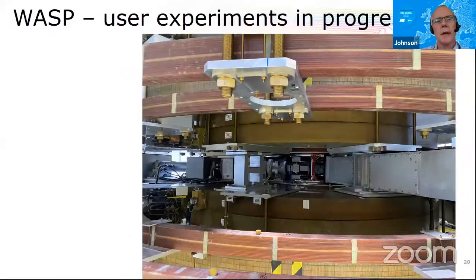So a new instrument, no X-ray capability in this case, wide-angle spin echo. So this instrument has taken some time to deliver. It was a very, very challenging project, but now it's in user service, doing user experiments. For those of you who know spin echo, you normally see the big magnetic coils horizontally disposed in the scattering plane, and that traditionally or typically limits the solid angle of detection, and that's one of the handicaps of the spin echo technique.